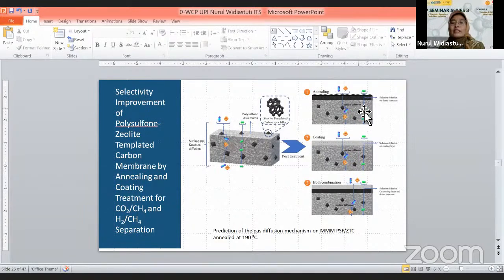For the annealing process, the key important part of the membranes is the surface area of the membranes, which is possibly where gas transfers through using the solution diffusion mechanism, where the coating process is a solution diffusion on the top of the membrane with the dense layer over here. When we combine both modifications, we find the solution diffusion on the top of the membranes with the dense layers, and also the surface membranes like we found in the annealing process.